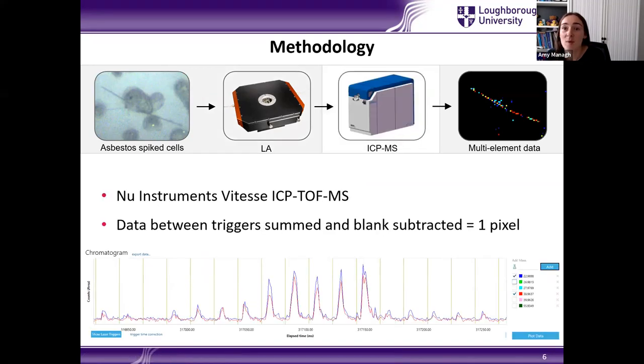And moving on to the ICP-MS step, a lot of our preliminary work was done using sector field technology, but we found very quickly that that wasn't really adequate for this application. So we moved on to using a time of flight mass spectrometer, the Vitesse from Nu Instruments. What this allows us to do is to measure from sodium through to uranium in 25.5 microseconds. So very rapid scanning of the whole mass range, really. 40 of these consecutive scans were summed together to give us data points at 1 millisecond intervals, which you can see on the data on the bottom of the slide.